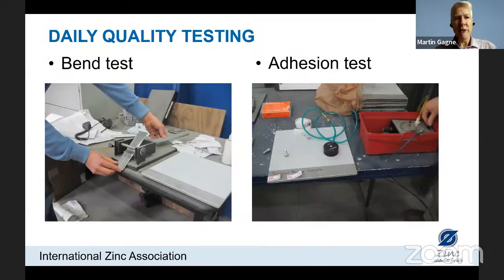So every day they did quality testing. So we've talked about both of these tests. We can see the bend test. This is a thin steel coupon that will be sprayed every day by the operator. So this is a way to ensure the qualification or quality of the operator, and then also the quality of the work. This will go through the bend, and again, cracking is acceptable, but flaking is not acceptable.